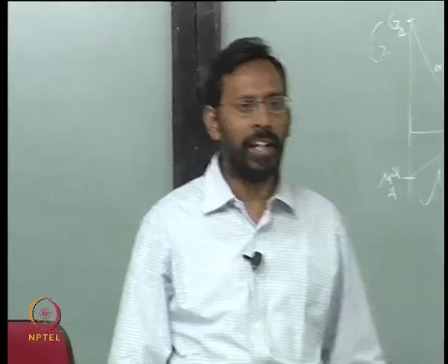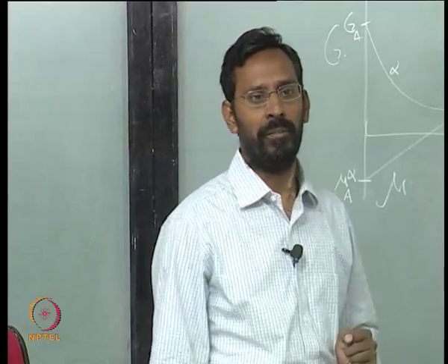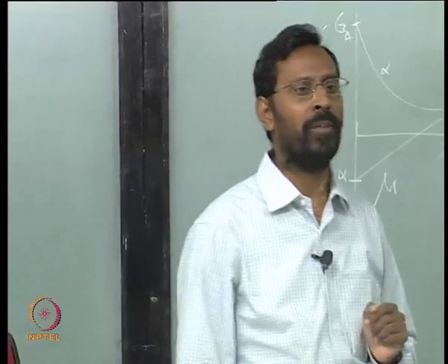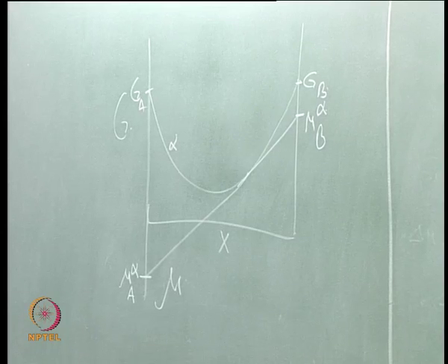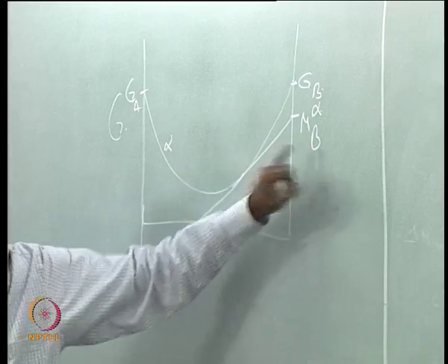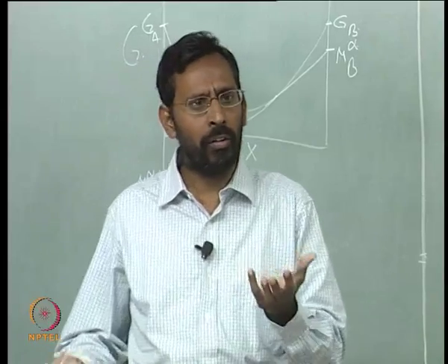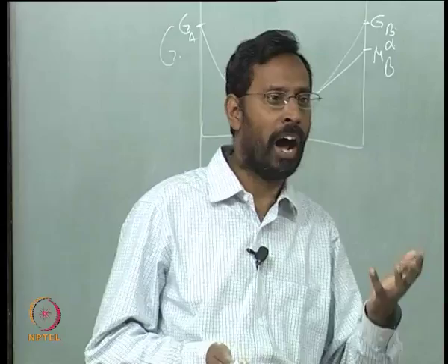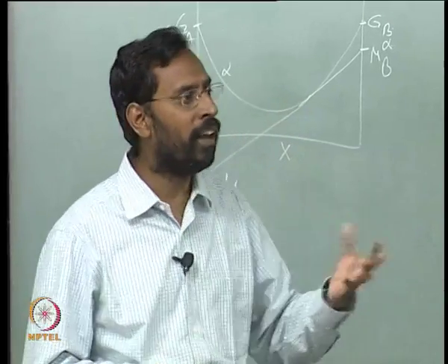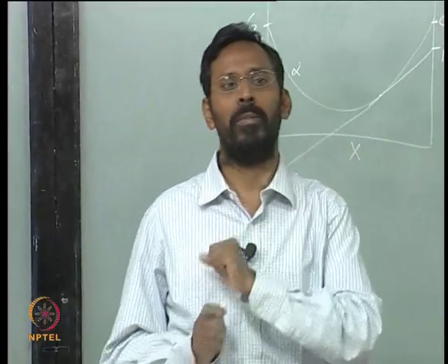Chemical potential indicates what is called the activity, because there is a relation between chemical potential and activity. You must have seen the equation RT ln a. So, chemical potential is always related to the activity. Whenever the chemical potential of a particular element in a phase is higher, we say that element is more active in that phase.